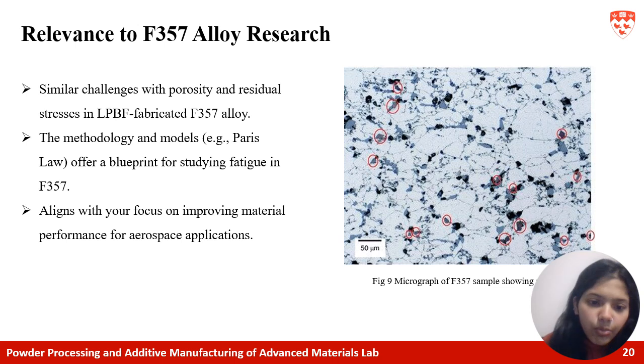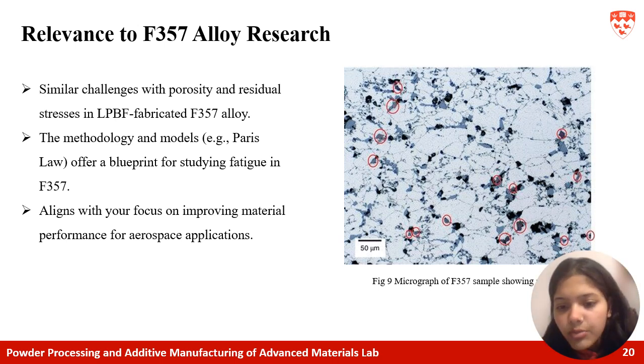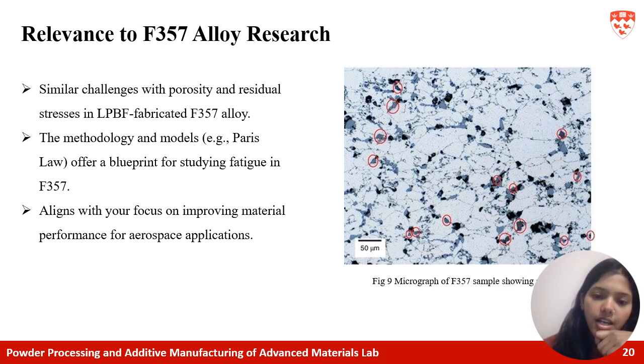So in a nutshell, we do face the similar challenges of porosity and residual stresses in the F357 alloy. And the methodology and models, they offer a blueprint for studying fatigue in future, and it aligns with my focus on improving the material performance for aerospace application. Here you can see in the micrograph, which was taken by me during my research, that there are various areas with pores, which shows that the F357 is in fact very similar to the aluminum silicon 10 alloy.